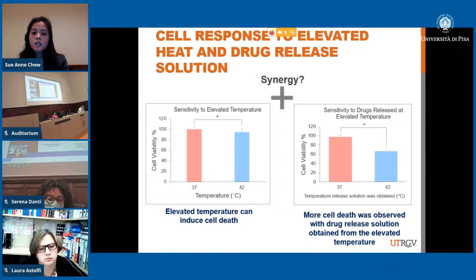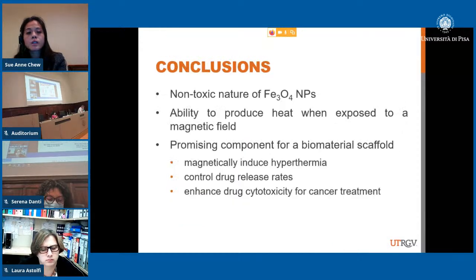So, our question next is, can we see a synergy in this? Is it the heating of the cells as well as the drug being released from the scaffold? Can we see a synergistic effect? So that's what we're exploring next. So just to conclude, the non-toxic nature of the iron oxide nanoparticle makes it a good candidate for us to use. By heating it, we are able to induce hyperthermia. We can control the drug release rate, and we can enhance drug cytotoxicity for cancer treatment.